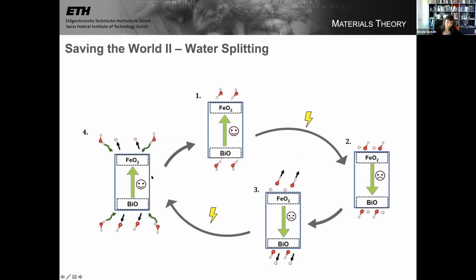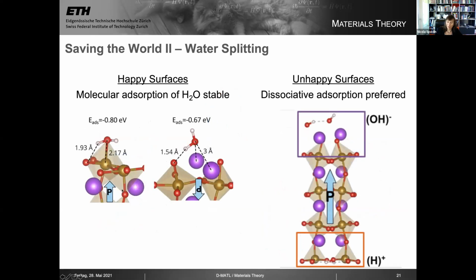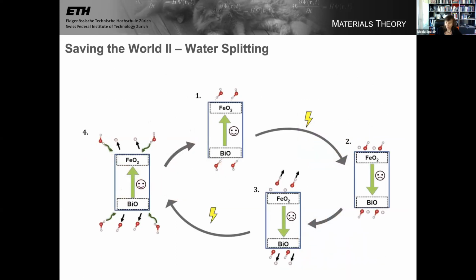Then you let the film relax back. The charged ions are released, they're spat off the surface, it no longer wants them, and molecules are reabsorbed. So one has this nice cycle for water splitting. I don't have the data to show you for this yet. I can tell you it's been done, but it's not yet published by our experimental colleagues.